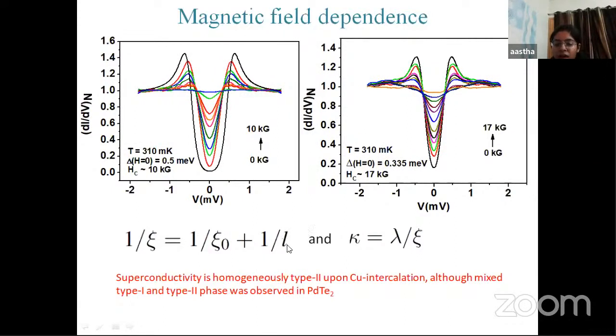Because what happens if we introduce disorder in the system, upon intercalation or upon introduction of disorder, the mean free path decreases, and hence a consequent decrease in the coherence length is observed. And this leads to an increased kappa, increased in such a way that the system becomes homogeneously type 2. We can say that disorder has pushed the system from type 1 to type 2.